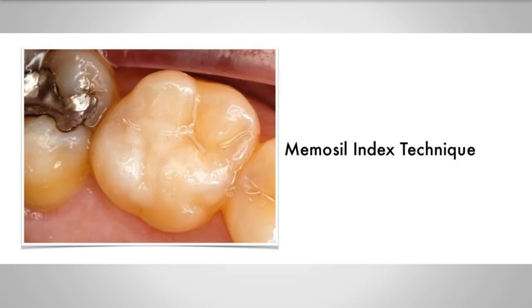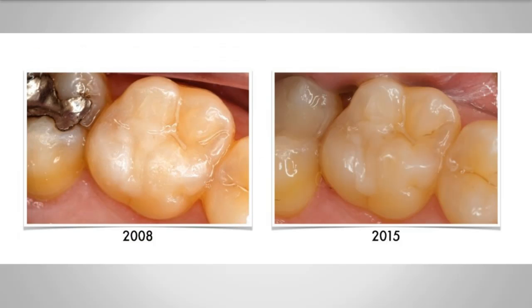That then requires very, very minimal finishing, like so, and polishing with an OptiShine polisher. That's all we did. And that's the case in 2008 when I did that case originally. I see the patient every 6 months, every year or so for his routine examination, and that's the case in 2015. So it's not had any detrimental effect, as I can see, on the composite, on the material itself. It's all functioning perfectly well.